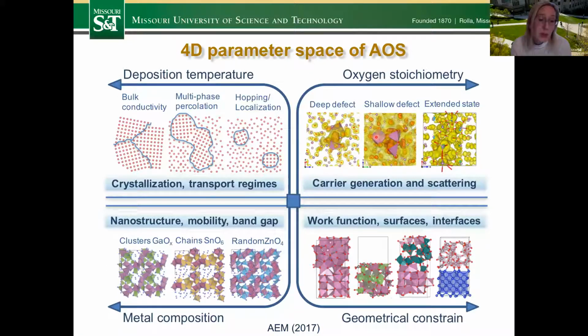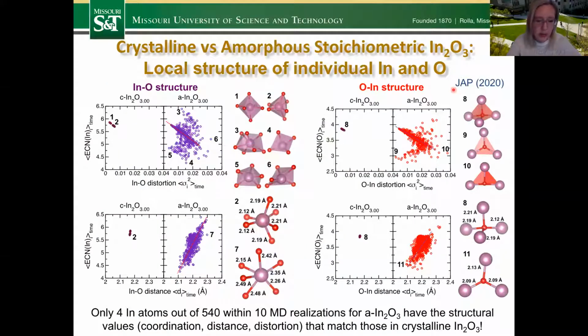So far we talked about the deposition temperature and metal composition. Let me now go into the oxygen stoichiometry and look at non-stoichiometric cases and defect formation. First, I'm comparing the crystalline and amorphous stoichiometric indium oxide and looking at the local structure of individual indium and oxygen atoms. Of course, we also have a distribution in the coordination number. Here is the coordination as a function of distortion of the polyhedra, and the coordination as a function of distances in the first shell, for the indium or for the oxygen. Oxygen is probably more significant because it's a p orbital, so it's a more directional bond. There are more preferences for the angle and coordination in general than for indium, which is an s orbital.